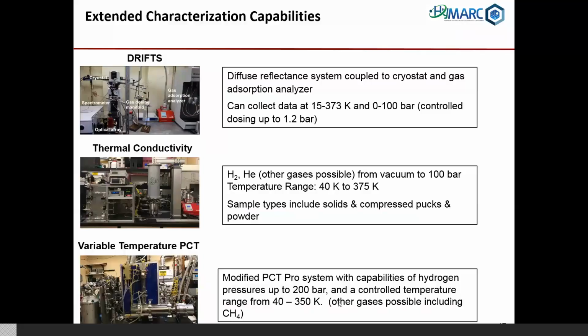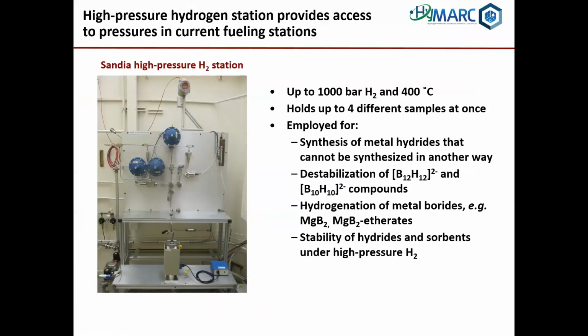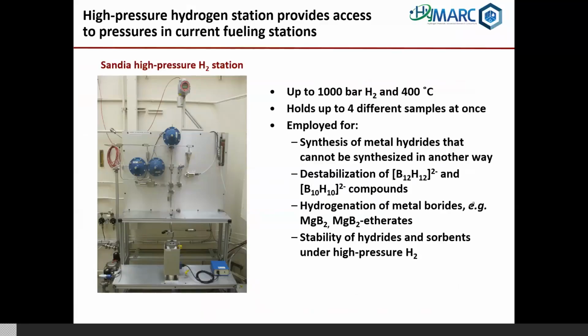Next slide, please. So this is also one unique characterization and synthetic instrument that we have. This is the high-pressure hydrogen reaction station at Sandia, California. This instrument, I was informed yesterday, can go up to 1000 bar and hold up to 4 samples and heat them up to 400 degrees C. What's interesting about this is that it provides us a way of looking at the behavior of materials at pressures that are now accessible in commercial fueling stations. Not that we necessarily think that 700 bar is the optimum, but it is interesting to us to be able to push these materials as far as we could conceivably go with available commercial equipment. In some cases, this may allow certain metal hydrides to meet DOE targets that could not make those targets back when the limit was something like 100 bar.